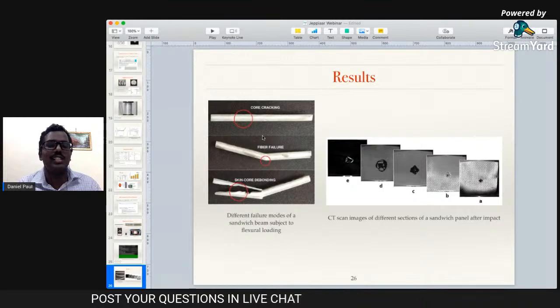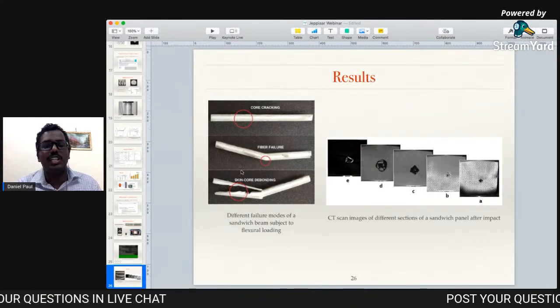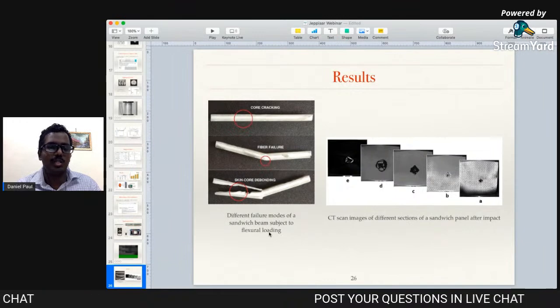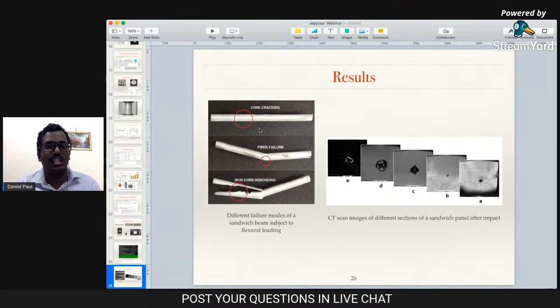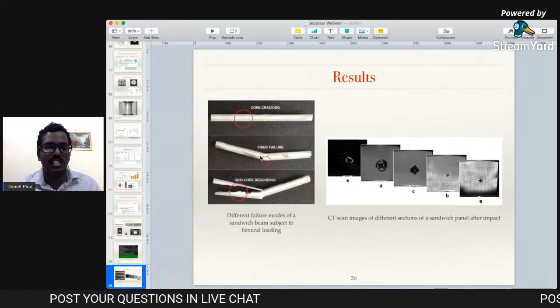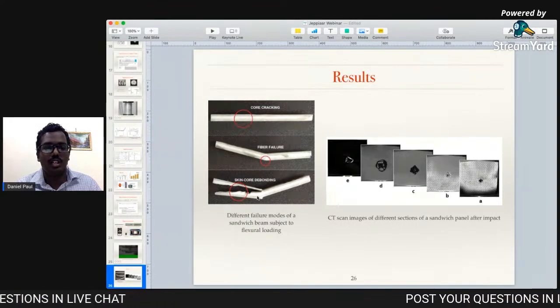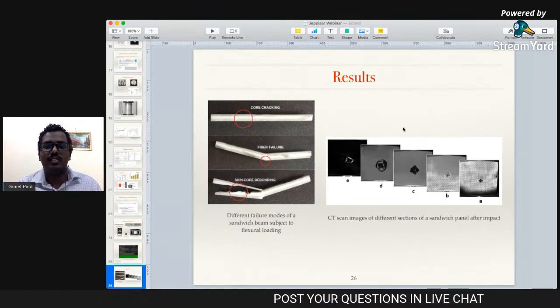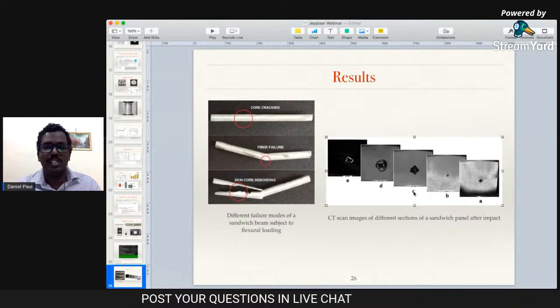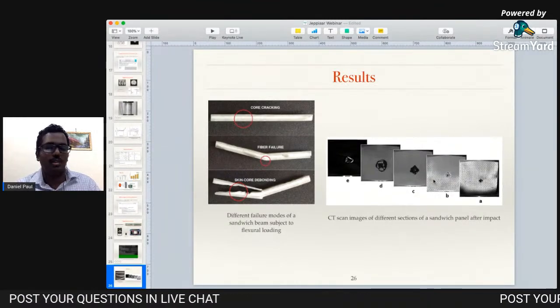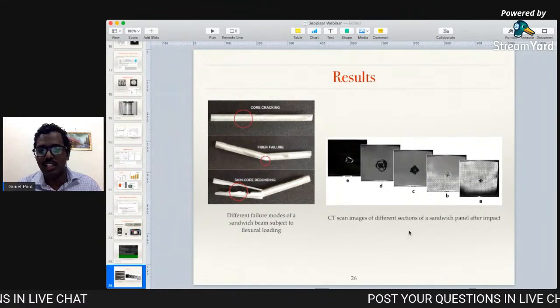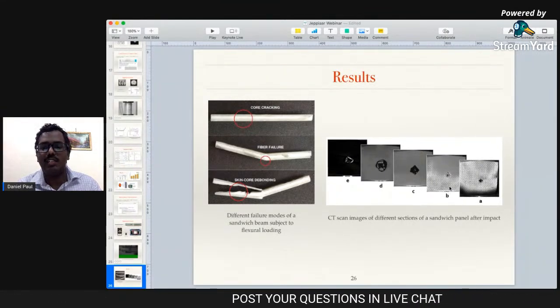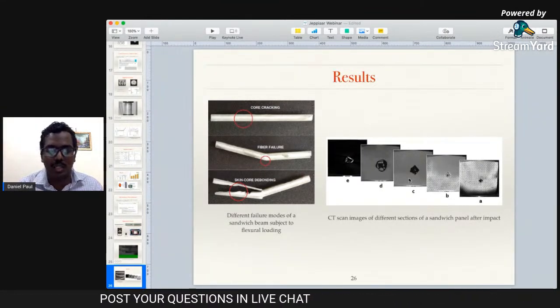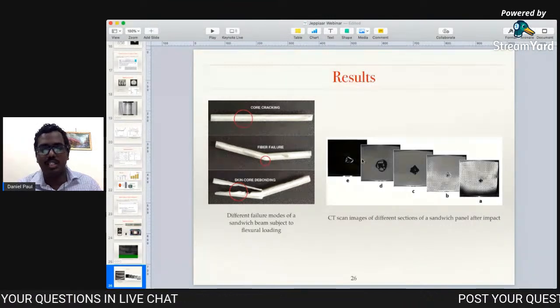So this again, as we saw in the load displacement graph, increased the area under the load displacement graph and caused a higher energy absorption capacity for this particular co-cured composite. And for the sandwich panels also, we had a lot of numerical results, which I'm not going to discuss here. And this is just a CT scan of different sections of a sandwich panel after the impact of the projectile, complete penetration of the projectile.